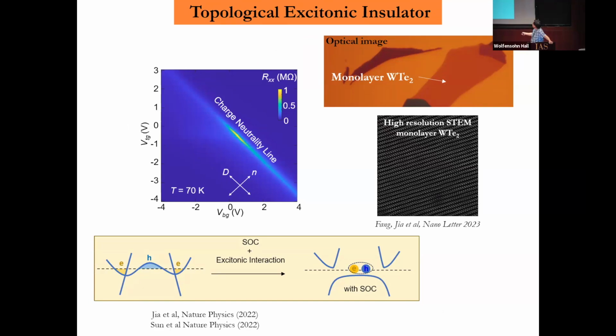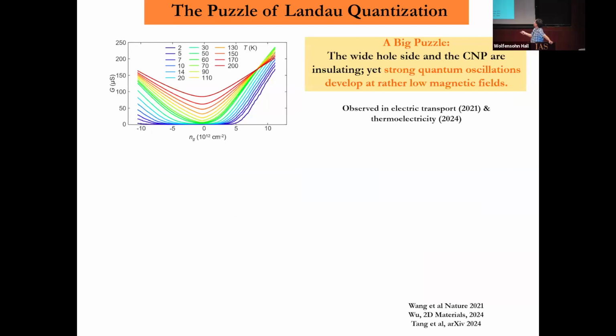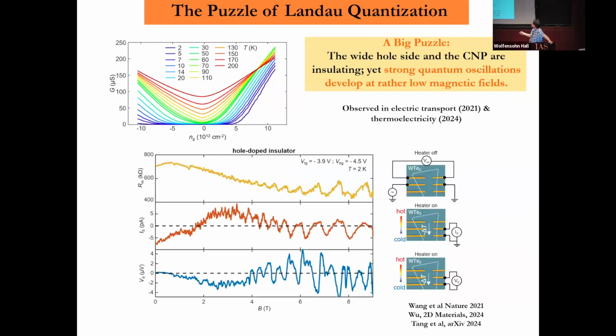On the hole side, what we know is that if we measure the density of states, it's very huge - so it's really strongly correlated there, with a very high peak in the density of states. What we experimentally observed is a wide range of hole doping where you have insulators. And in these insulators, there's a very puzzling quantum oscillation that develops in the insulating state. We observed this both in resistance measurements and in thermal power, where you apply a temperature gradient and measure the voltage drop. Both resistance and thermal power show consistent oscillations. This is very hard to explain without thinking it's intrinsic to the insulator.